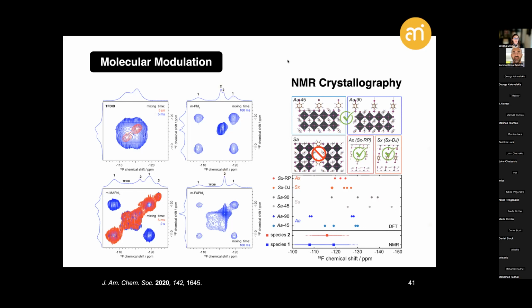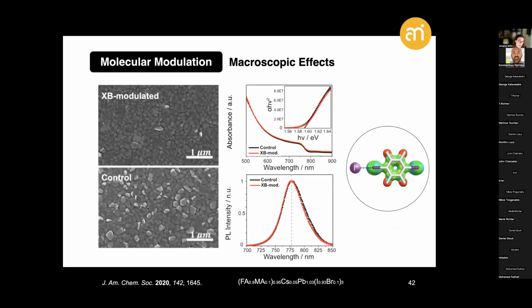But at this point, one might wonder, how do these atomic-level interactions, especially these weak interactions, truly affect the macroscopic properties of these materials? Well, looking more carefully into their morphology, for instance by scanning electron microscopy, we do not really see major changes in the morphology of these materials in the presence of these relatively weak and substoichiometric amounts of the corresponding modulators, which is also reflected in the optoelectronic characteristics, which are not in any way compromised in the presence of these modulators, in this case in a conventional triple cation double halide perovskite composition.